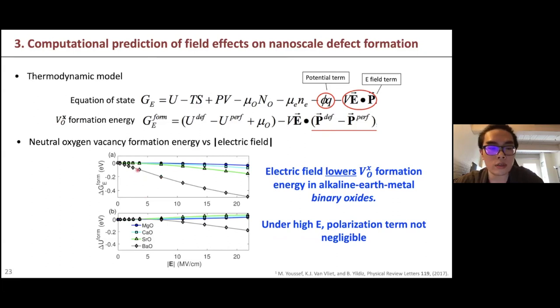As you can see, the relative formation energy drops when you apply the field. For barium oxide it's very obvious, and it drops around 0.3 eV when the field is around 10 megavolt per centimeter. So here I just want to say that the electric field term becomes very important when the field is very high, and this is what we are going to ask for the more complex oxides next.